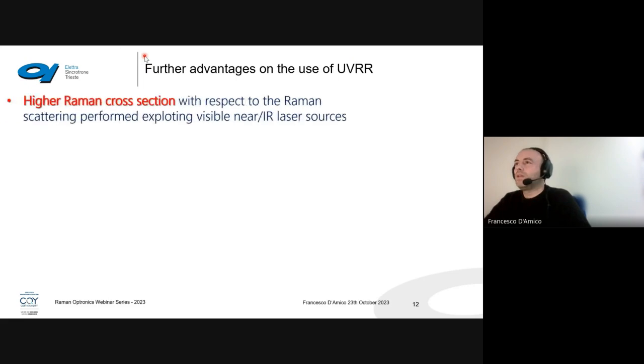The UV resonant Raman, apart from the enhancement of the Raman signal due to the resonance, possesses further advantages, which must be taken into consideration. The first one is that obviously the Raman cross-section goes as the inverse of lambda to the fourth, where lambda is the wavelength of the excitation source. So in the ultraviolet, we have a small lambda and a higher cross-section. And therefore, we should have a signal with a higher signal-to-noise ratio with respect to the visible one.